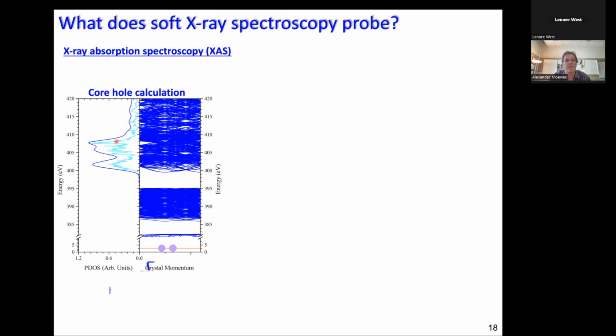I think most of you will know that when you now come in, and here you see the nitrogen 1s in this case, probing the conduction band. Upon careful selection of your incoming energy, you take a nitrogen 1s electron and promote it to the conduction band, and not a surprise, X-ray absorption spectroscopy in this case probes the unoccupied partial density of states. Now we have, of course, an excited system with the additional electron here and the hole here in the 1s shell. And like any good physics system, this shall decay. Now, of course, if the same electron would go down, this would only give rise to elastic scattering. Energy in is the same as energy out. So that's not interesting, at least to us.